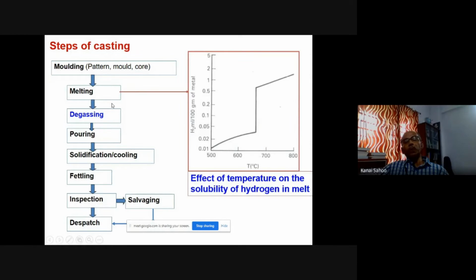So melting, the moment you do melting, the liquid metal has a high tendency to absorb gas. So imagine for aluminum alloy, over the melting temperature, it's already 1 cc per 100 gram, so for 1 kg, that is 10 cc of absorption of hydrogen. It's huge. The moment they will solidify, the solubility of hydrogen in aluminum is very less. So all these gases have to go out. And most of the people, most of the researchers, most of the students, they don't take care to reduce all these gases. As a result, the moment you do casting, all the gases are included in the final casting, and they have very less properties.